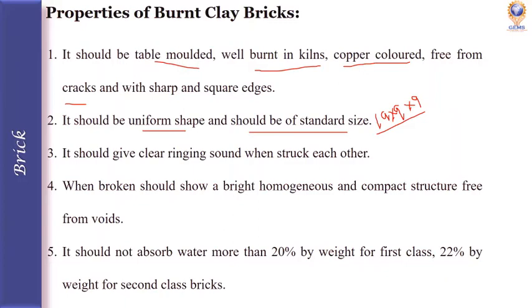Next, when you break the brick in half, its inside should show a bright, homogeneous and compact structure free from voids. If it is not a bright, homogeneous structure and voids are present inside the brick, the strength of the brick will be lesser. It should also not absorb water more than 20% of its weight for first class and 22% for second class brickwork. If it absorbs water more than 20%, the brick is not good quality.